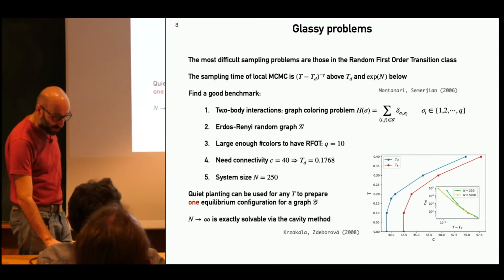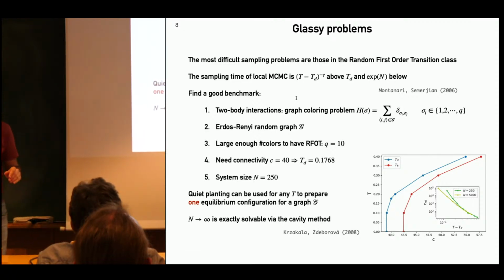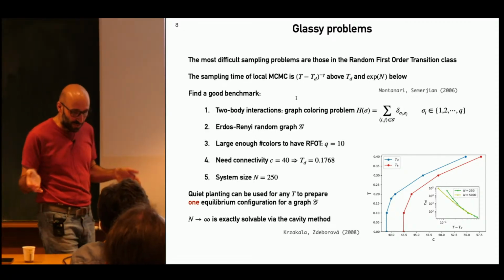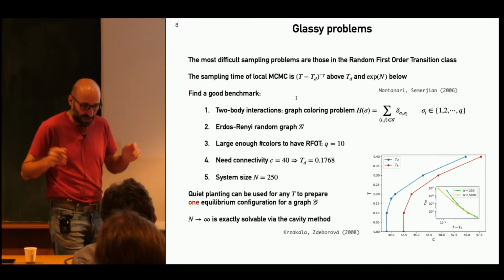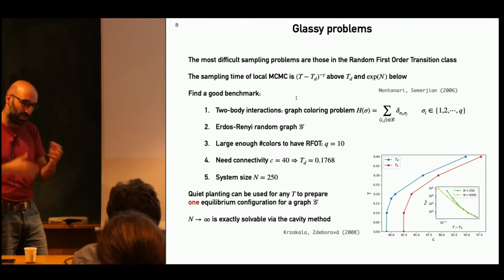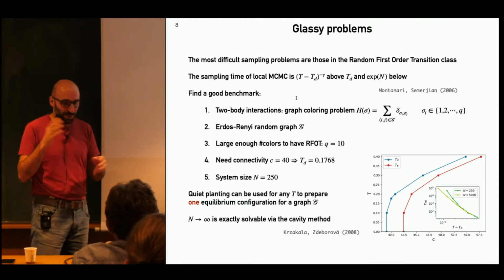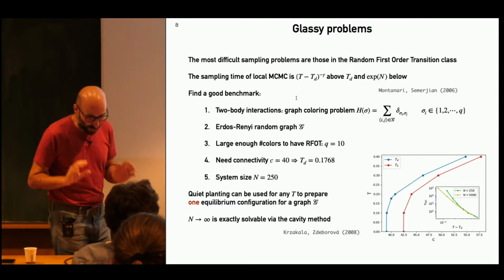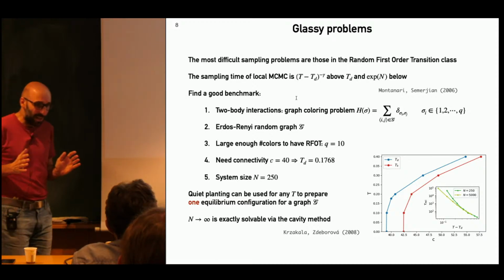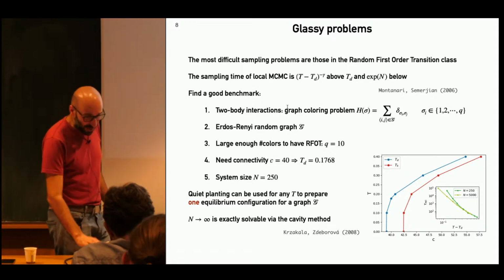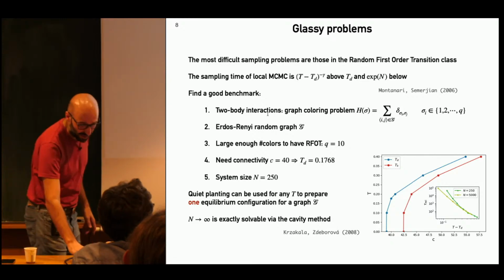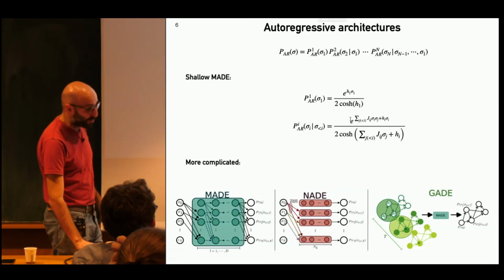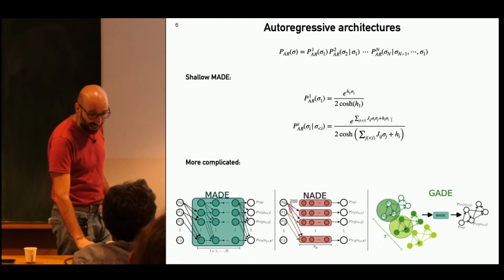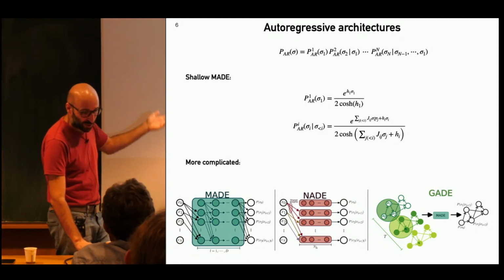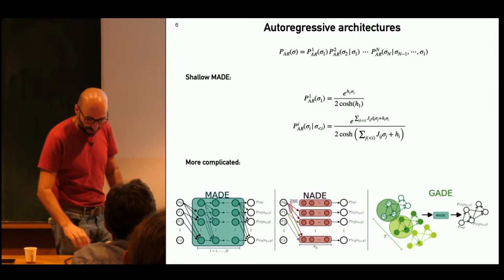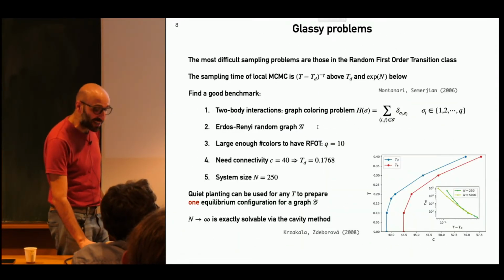First of all, we wanted to have two-body interactions. So we wanted to consider a spin model, because if you take a particle model, you have to go to high dimensions, and then you have continuous variables because the particles are continuous. When you want to build an autoregressive model with continuous variables, things get more complicated. So we wanted to be in the easiest possible case. So we took a spin model with two-body interactions, and the reason is that we wanted to use this kind of architecture for the auxiliary model, and this naturally has two-body interactions. You could add three-body interactions, but then you would have more parameters and so on. So we said, let's stick to two-body interactions.